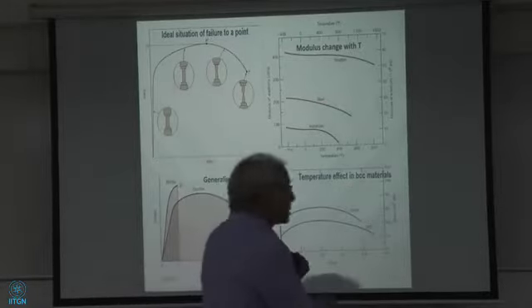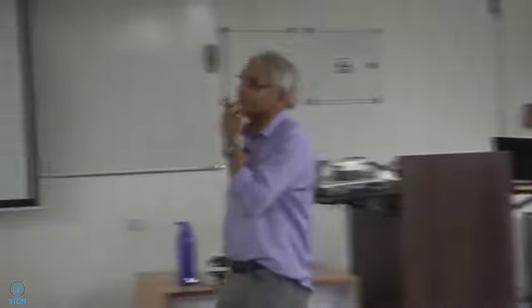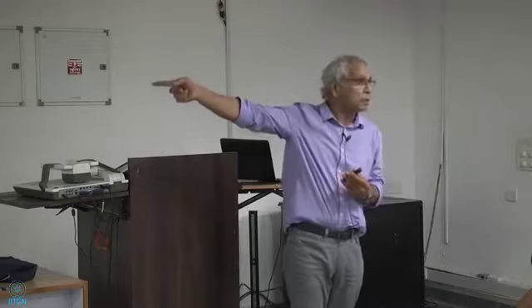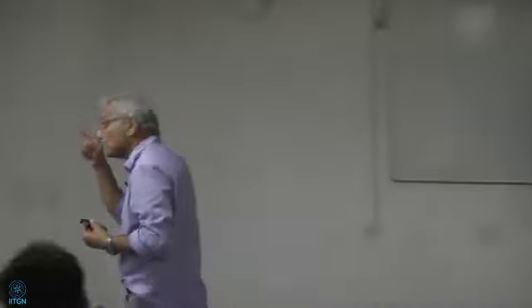In body-centered cubic materials, this is a very specific, very unique property of body-centered cubic materials like iron, vanadium, steel, beta titanium. Aluminum is face-centered cubic. Those BCC materials show a very strong effect with temperature. Their yield strength changes very strongly with temperature. So lower the temperature, higher the yield stress in the case of body-centered cubic materials. It does not happen so easily in FCC materials, but in aluminum lithium it happens. That's why aluminum lithium is so unique.